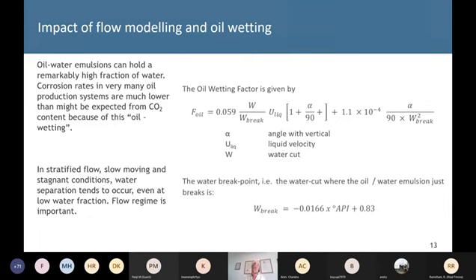And related to this, we have the question of water separation. Oil and water is flowing along the bottom of the pipeline, and it will be carrying the water in an emulsion, which is actually completely contained. If you look at the structure of an emulsion, as long as the water is inside the oil, it's surrounded by oil particles, molecules, and these are protecting the water from actually impinging on the steel surface. But when we have stratified flow, we have slow-moving, possibly stagnant conditions. It can take days for a molecule of water to get from one end of a pipeline to another. It's held up at various places, and in those conditions we can get water separation.